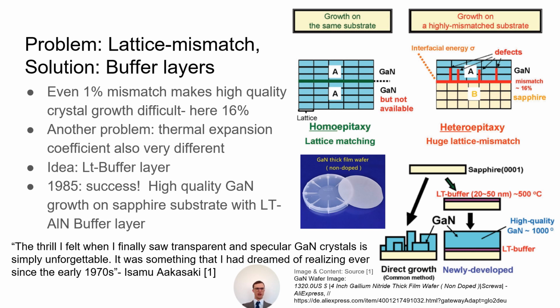They used what is known as a low temperature buffer layer. Low temperature just means the buffer layer is grown at a lower temperature than gallium nitride, but what's really relevant is that it makes the lattice actually match, because the buffer layer at the substrate matches sapphire, but then at gallium nitride, it's kind of like the lattice in the buffer layer gets larger as it goes to gallium nitride. And this is a really genius idea, and due to this, Akasaki was actually able to realize his dream of transparent gallium nitride crystals.